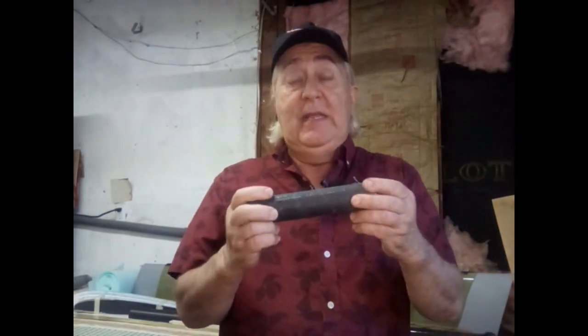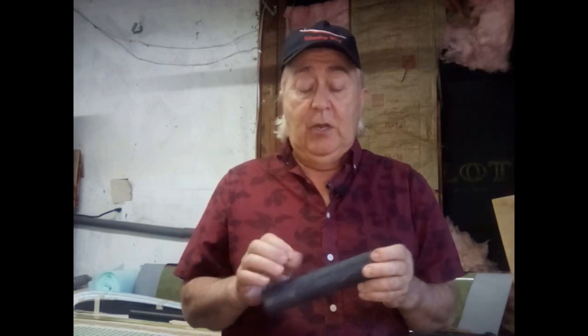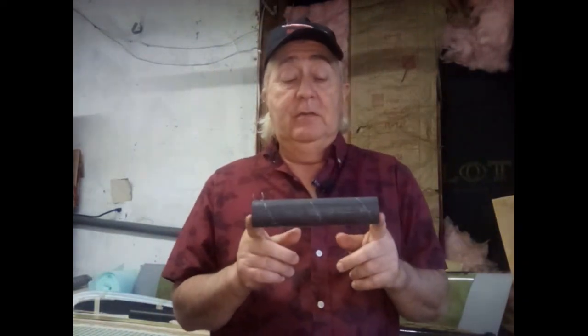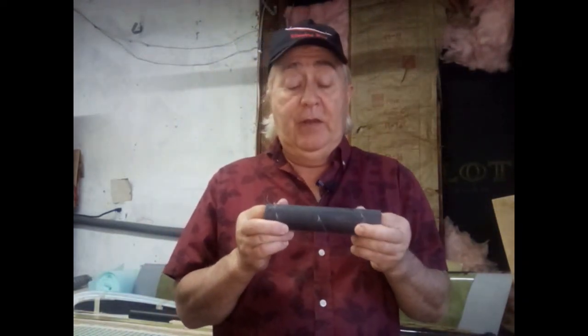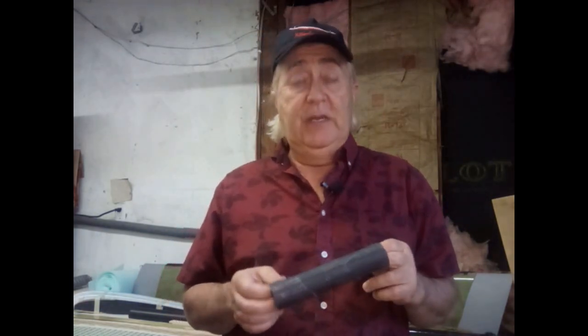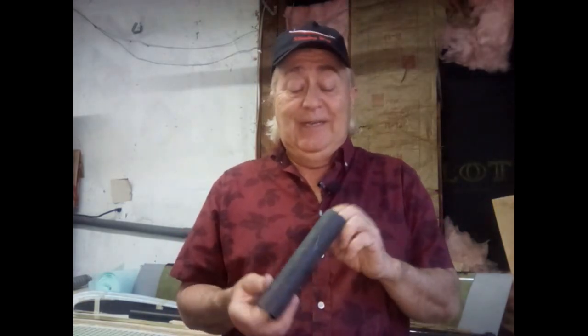Here's a piece of 1.5-inch diameter tubing that I made that is 1 layer thick of 6-ounce cloth. And this is about, what did I have on this? There it is. This is 1/2 ounce per foot. This is going to be lighter than aluminum tubing of the same diameter, of some other thicker wall thickness, and it'll probably have the strength of aluminum tubing that might be 30 thousandths. Before when I say tenths, I'll put a little thing up on the screen. Not tenths, thousandths, 30 thousandths.